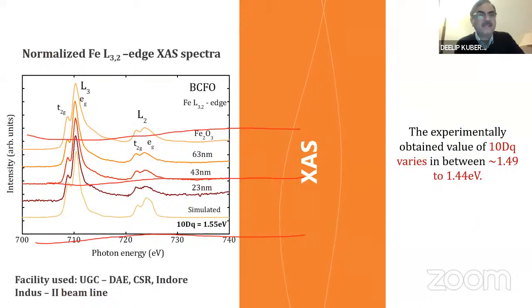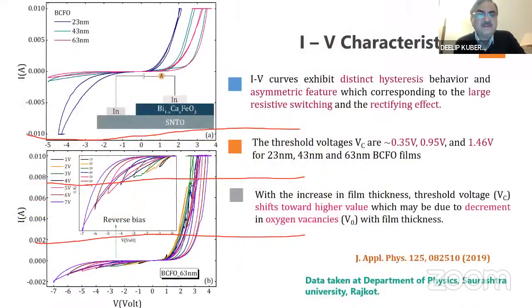So therefore, we normalized the Fe L3,2 X-ray absorption spectra, again at the same facility, Indus-2. Here, interestingly, we observe the crystal field splitting. The value of the 10Dq crystal field splitting varies between 1.49 and 1.44. Theoretical and experimental values match with each other, which can be understood after normalizing and analyzing this data. Then, coming to the application side, after the modifications in the electronic structure as a function of thickness, we studied the IV characteristics.